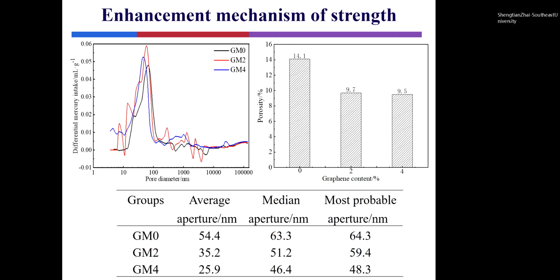This picture shows the pore size and distribution in the hydrated cement matrix. The porosity of the hardened mixture was significantly reduced with the introduction of the graphene. When the content of the graphene was 2 weight percent, the porosity was decreased by 31% compared with the standard sample. This picture shows that the small size pore increased first and then decreased, and the largest size pore was basically the same. This result illustrated that the graphene particles were filled in the large pores of the cement paste to form a plugging effect, and the number of the small pores has increased within certain regions of the graphene content.